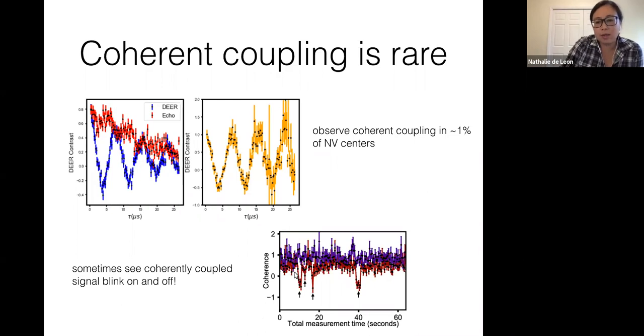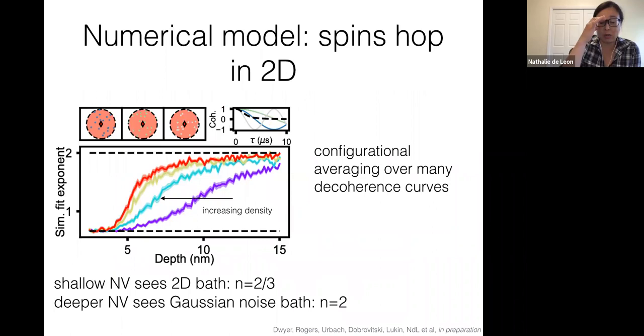And intriguingly, there are a few special NV centers where you could see a coherently coupled signal that blinks on and off on human timescales. So it shows up and then disappears after a few seconds. All of these observations led us to a model where maybe what you're seeing is not actually a static bath of spins, but many different configurations of this 2D spin bath. And then instead of being able to see this coherent coupling, you're actually just averaging over many, many decoherence curves. So one question that we had is, can this kind of model explain all of our different puzzles?